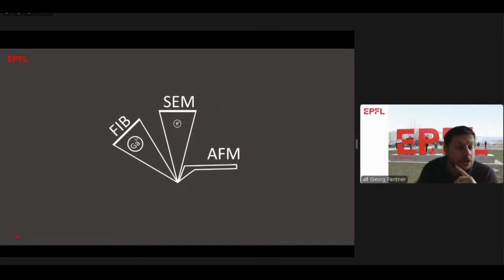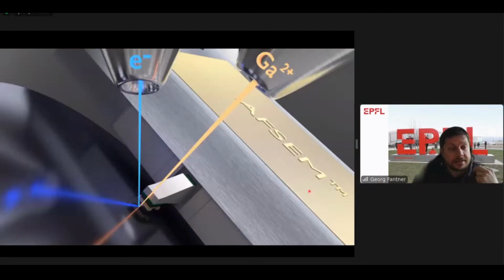Or even better, it could be combined with focused ion beam microscopy, so that we can get AFM mechanical properties and topography contrast, SEM we can use for imaging materials contrast, for example through EDX measurements, and focused ion beam can be used to actively modify the sample and look at those changes. And so several years ago, we started building these machines that can be put into a dual beam SEM FIB.